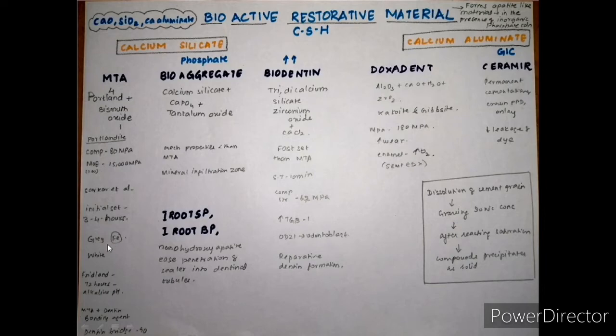Grey MTA produced twice as many hydroxyapatite crystals as white MTA in some studies, which leads to some speculation that grey MTA and white MTA may not possess the same level of bioactivity. According to Friedland et al., the MTA could maintain its high alkaline pH for about 72 hours, and the antimicrobial activity of this MTA is because of its alkaline pH.